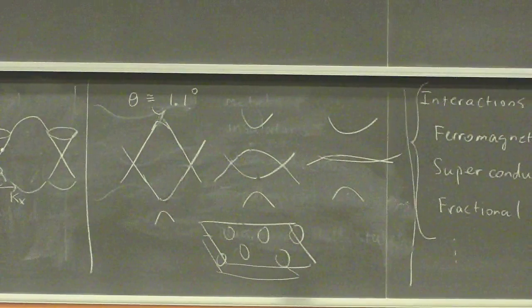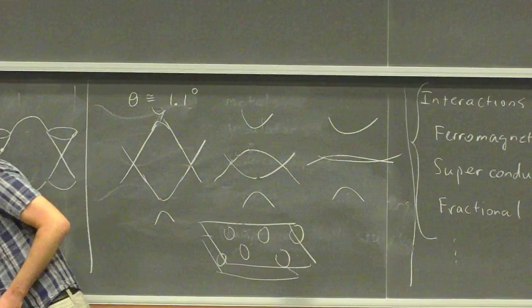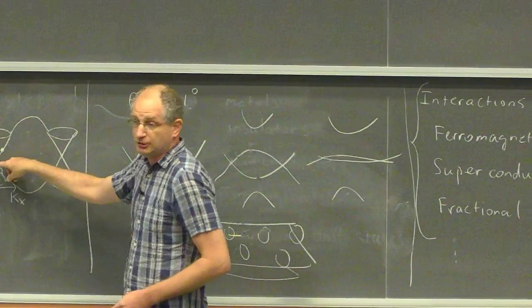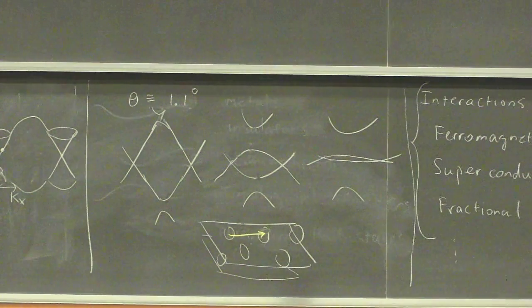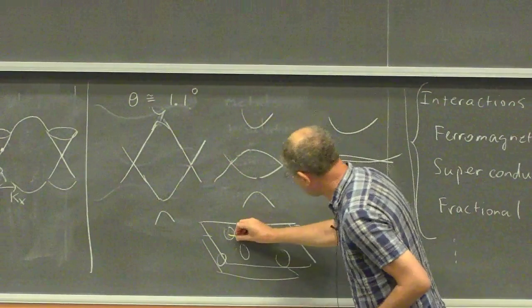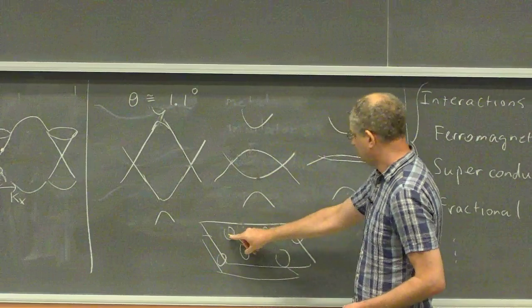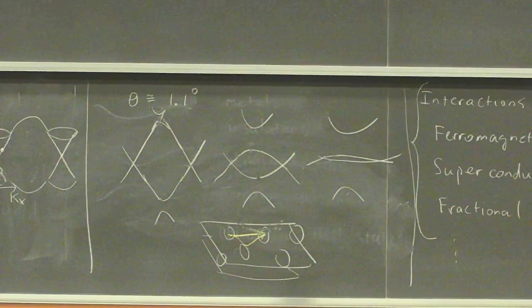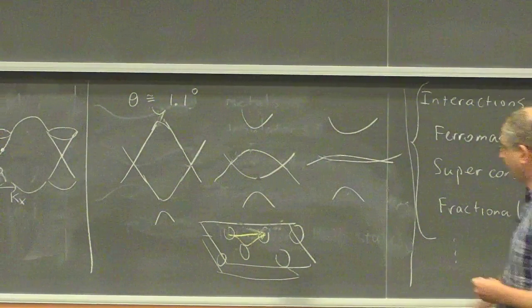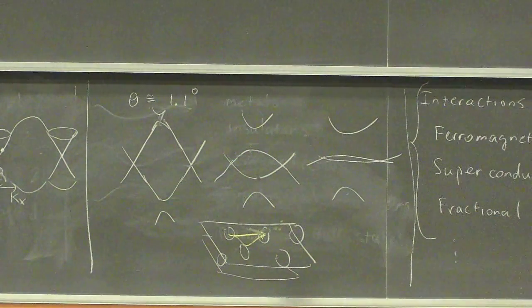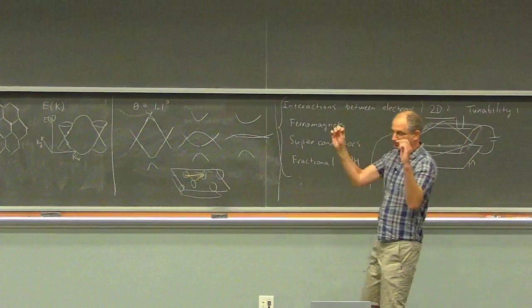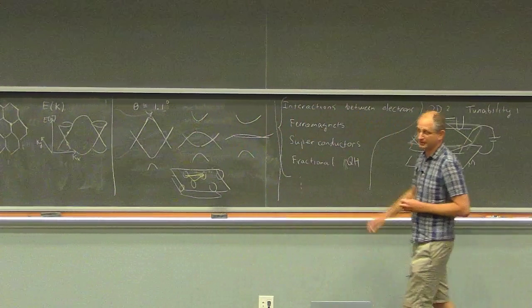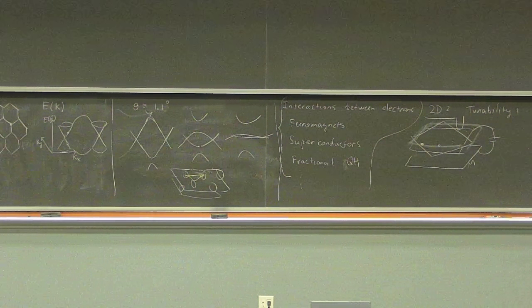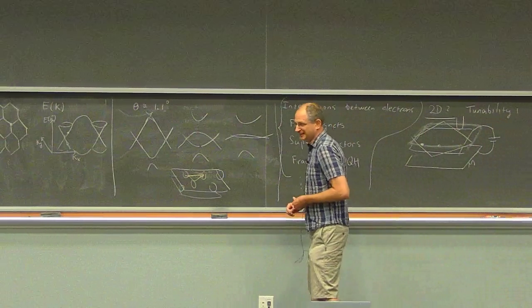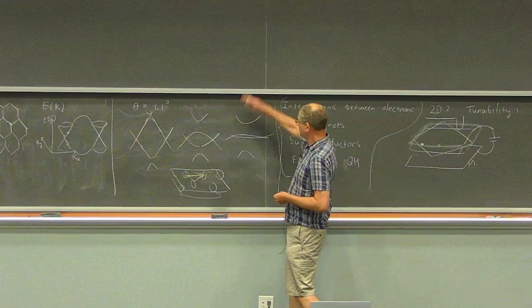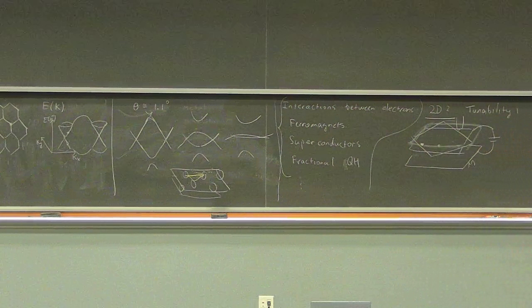There are two time scales in the problem. One is the time it would take an electron to move, with the speed of the original Dirac dispersion, from one lattice point to the next. And there's another quantum time scale, which is the time it would take for the same electron to tunnel to the other layer and tunnel back, which depends on a totally different parameter: the height of the potential barrier that the electron has to tunnel through between the layers, not within the layer. When these two things are resonant with each other, that's where the magic happens. So this is ultimately where this number 1.1 degrees comes from. And if you rotate a little more, it winds up, very rapidly in fact. You go just a few tenths of degrees, and this width would shoot up in both directions. So that was the prediction.